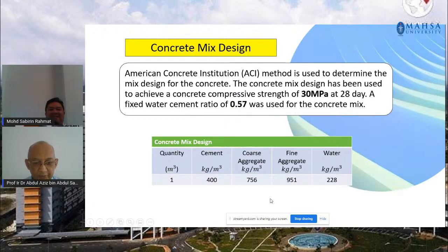Now this is the mix of the concrete. As you can see there, the cement is about 400 kilogram per meter cube, coarse aggregate at 756 kilogram per meter cube, fine aggregate, which is sand, is 951 kilogram per meter cube, and water, you require 228 kilograms of water in a 1 meter cube of concrete mix. Now this is the normal concrete mix. It has no waste material as yet.